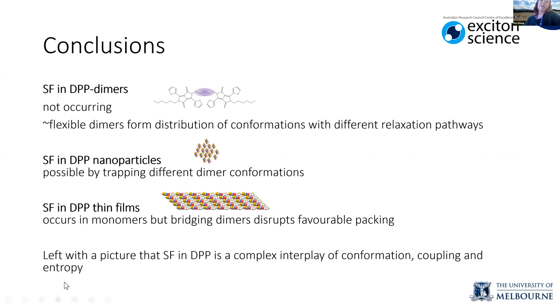And then lastly, there's always this argument of entropy. So if you can form two independent triplets through this singlet fission process, they're more likely to form in a film where they have a range of different areas that they can be in, and places that the charges can reside. Whereas when you're in a dimer, you're fixed, you're stuck on the dimer, and it's very easy for two charges to just recombine and go back to the singlet state. So it's always a bit more complicated in films because of this.